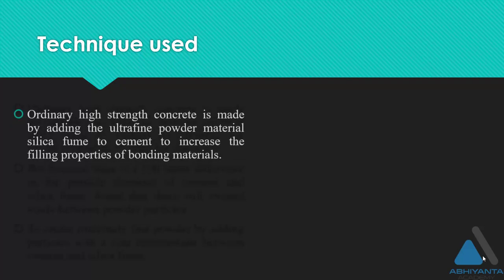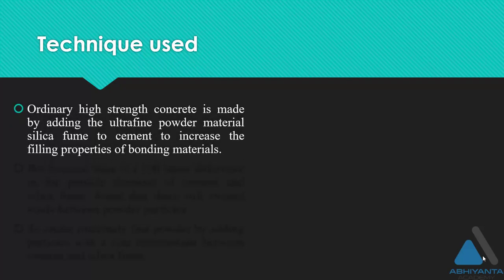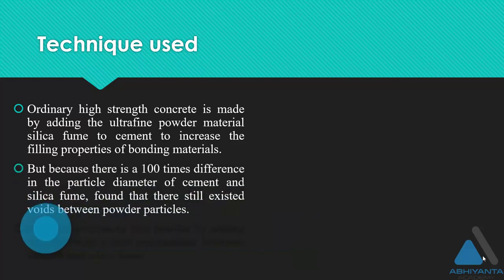Ordinary high strength concrete is made by adding the ultra fine powder material silica fume to cement to increase the filling properties of bonding materials. But because there is a 100 times difference in the particle diameter of cement and silica fume, it was found that voids still existed between powder particles. So in high strength or ultra high strength concrete, we have replaced voids by filling with silica fume, but there is a gap due to the variation of size, so it doesn't reach the highest strength. That's why we have modified that material.